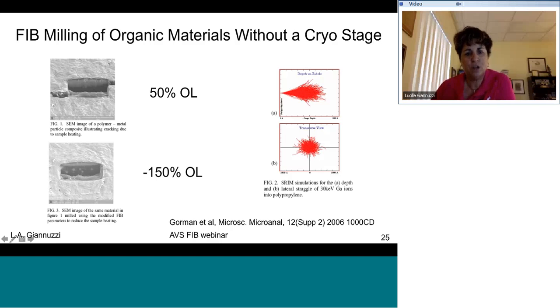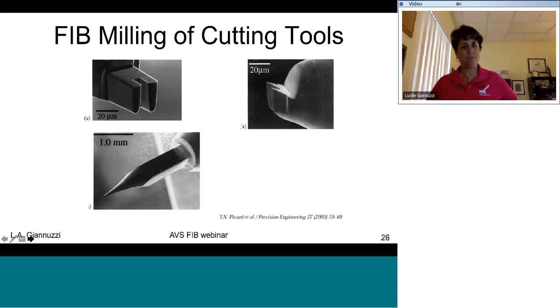polymer surface. So all you have to do is go to very large overlap, very large negative overlap. So you want to step the beam much further apart than have a 50% or zero overlap. If you step the beam at a much larger pitch, that's a much larger negative overlap, you can avoid the overlapping collision cascades, overlapping recoils, and FIB mill the polymers just fine without a cryostage.